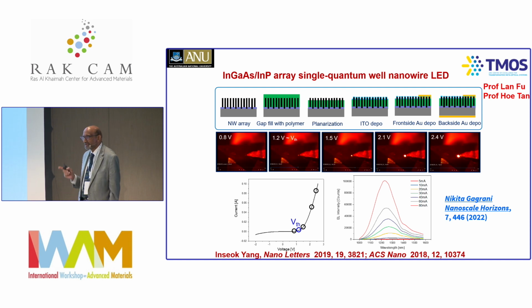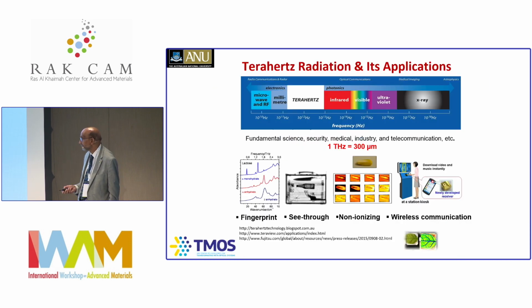Still, there is a problem in terms of making electrically injected lasers, and we're now exploring how to solve this particular problem. Another student, Nikita Gagrani, spent about 4 years replacing these metals with oxides. But despite that, one of the challenges is that for transparent conducting oxides, N-type oxides are fine, but P-type oxides are very difficult to make. And contact resistance leads to heat generation. If you generate heat, again, you're not able to make these lasers work. It becomes like a vicious circle. We are now redesigning and seeing how we can solve this particular problem.